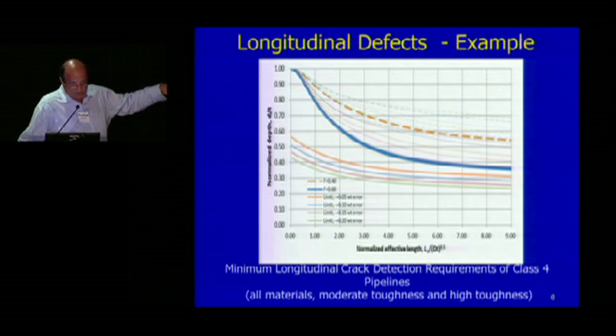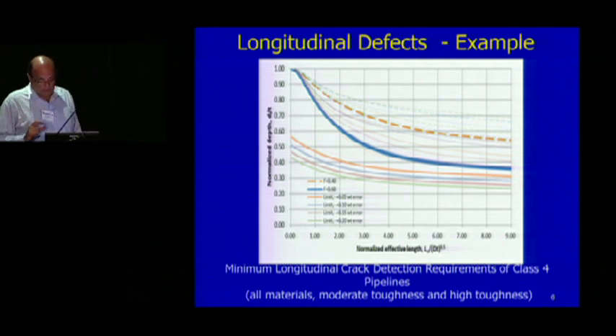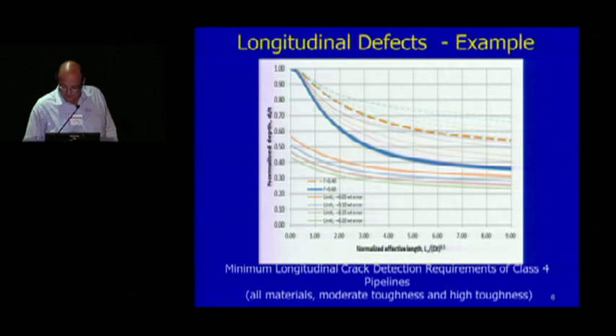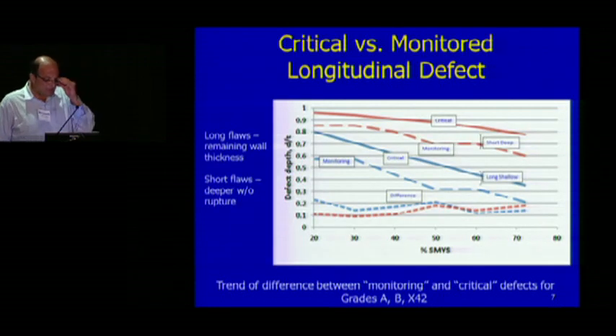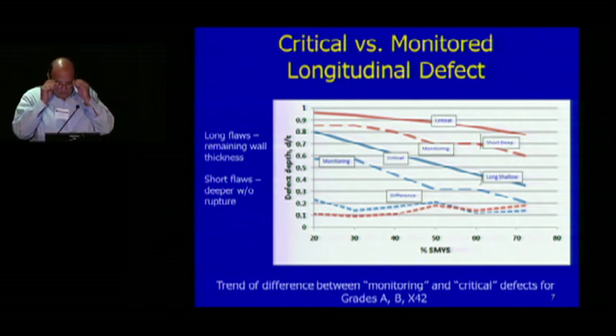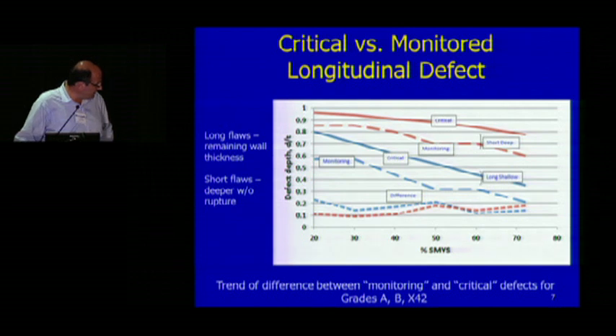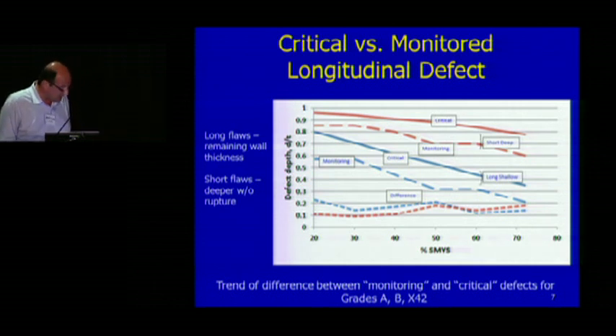And again, in this curve, also taken into account is the error that you always have in measuring the length of the defect. Okay? Something else, critical versus monitor longitudinal defects. And again, you see it for short and deep defects at the top, the red lines. Again, critical versus monitoring. Critical is the solid line, monitoring is the dashed line. And then the blue lines are those for long and shallow defects. And again, critical versus monitoring. And again, you see at the bottom, this is for a certain grade of materials.